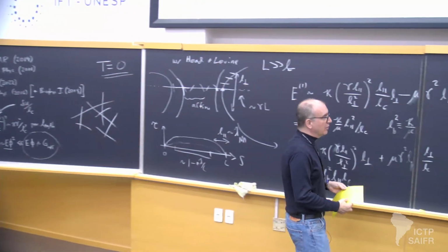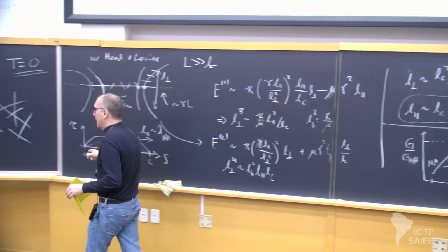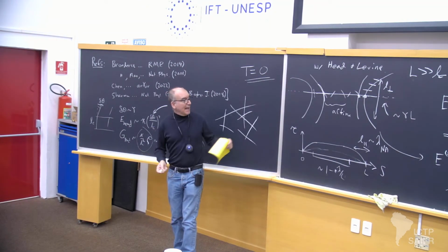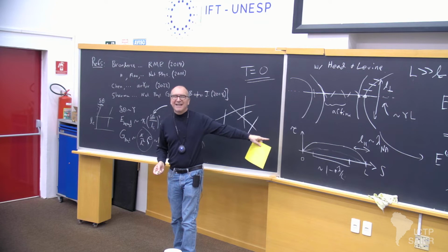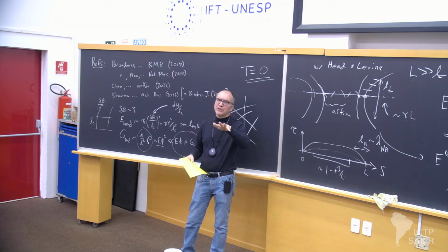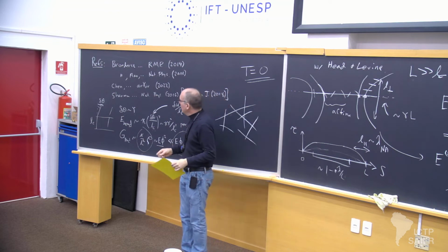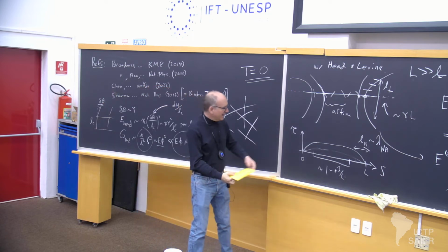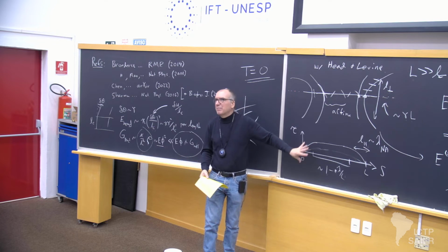And so one of the things you can do is go back to the thermal affine regime, which I talked about before, and add this. Not quite this effect. You have to do things a little differently. What you do is you take into account the thermal fluctuations of the nodes more consistently. And you will get a finite temperature and molecular weight dependent modulus. So that would be the realistic semi-flexible polymer network. That's one of the things that this paper does here. I won't go into that because the physics is already sort of apparent here.